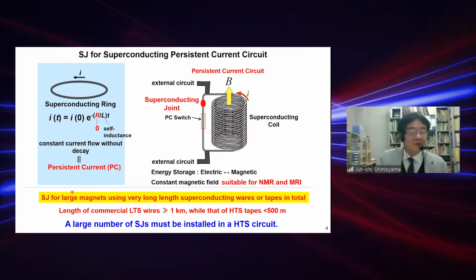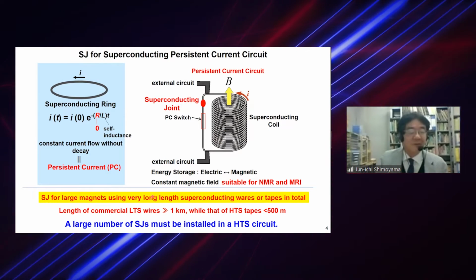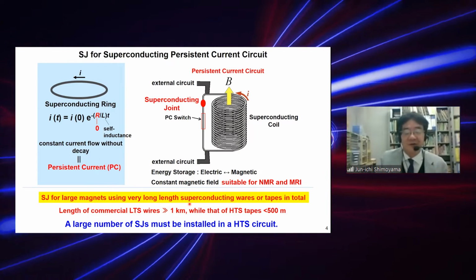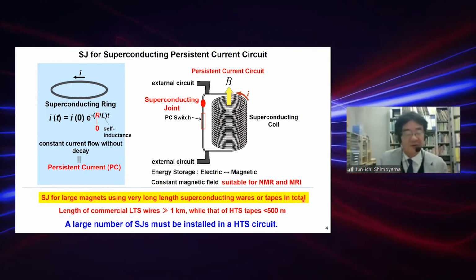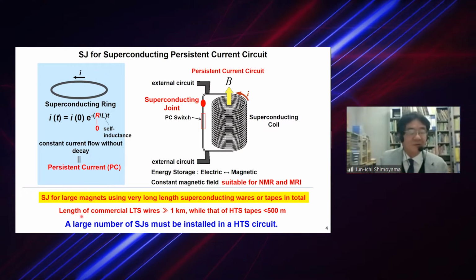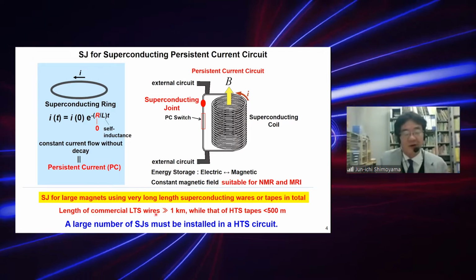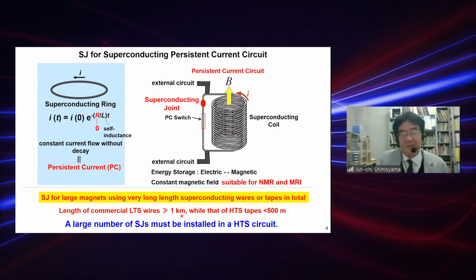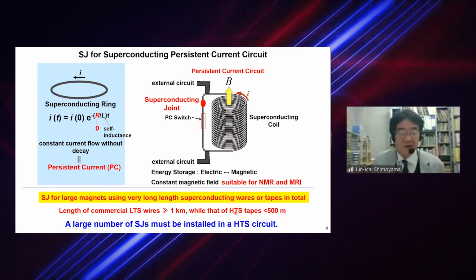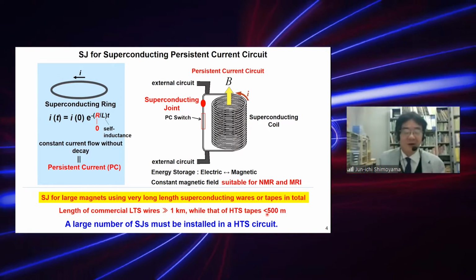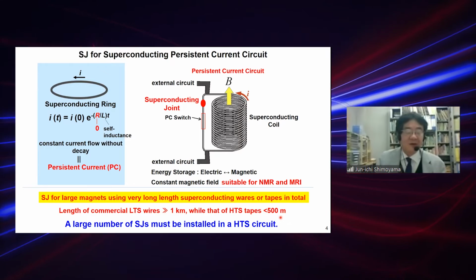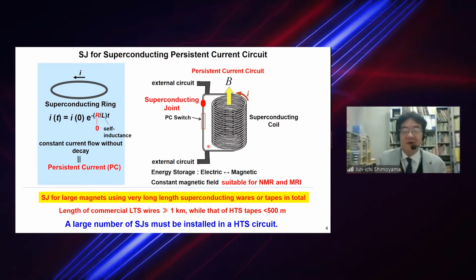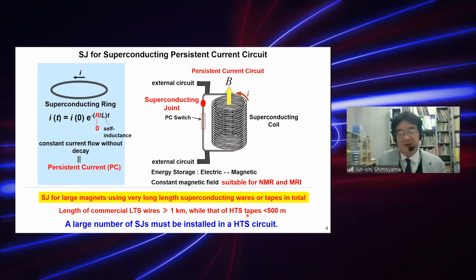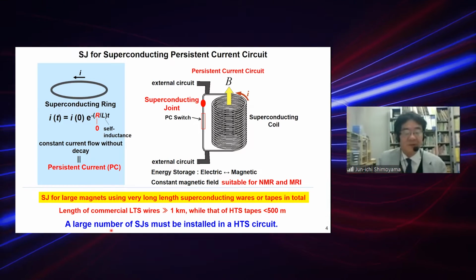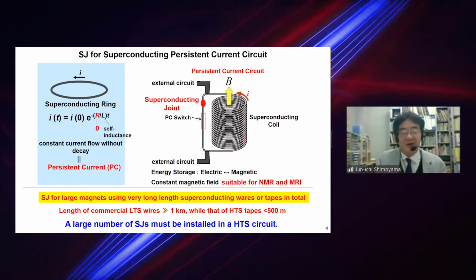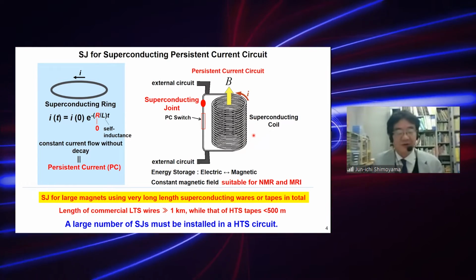So superconducting joints are needed for a large superconducting magnet using very long length superconducting wires or tapes in total. That means the length of commercial low temperature superconducting wires is usually longer than 1 kilometer. The point is that that of HTS tapes is usually shorter than 500 meters. So if we consider such a large superconducting magnet using HTS tapes, we need a large number of superconducting joints around this magnet. This is a very important point.